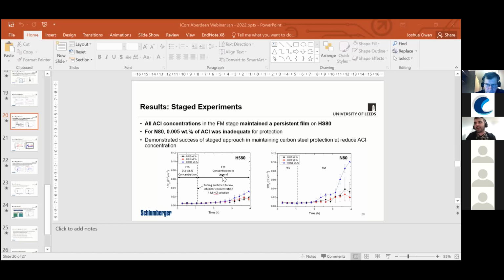Yeah, and that's one of the challenges of any electrochemical measurements with inhibitors, where essentially a film is formed on the surface. LPR doesn't always tell you exactly what you're expecting it to do, or how it's interpreted. I think one of the main challenges, with it being such an aggressive environment, is the duration over which you'd be polarizing with impedance spectroscopy. It would be interesting to look at to see whether or not we could actually identify the different mechanisms that are occurring. It would be particularly challenging in the flow cell environment, purely from the duration of the measurement that would be completed.